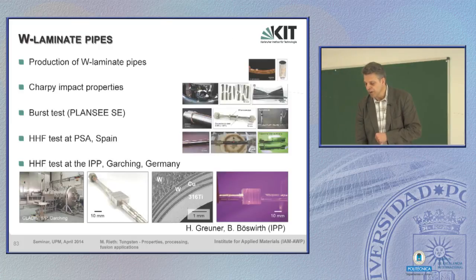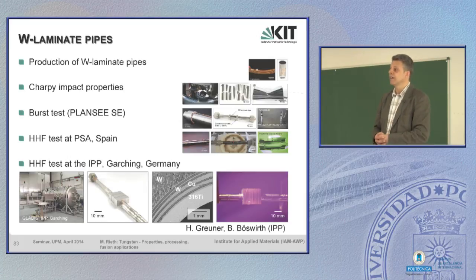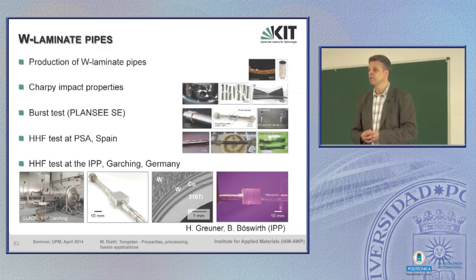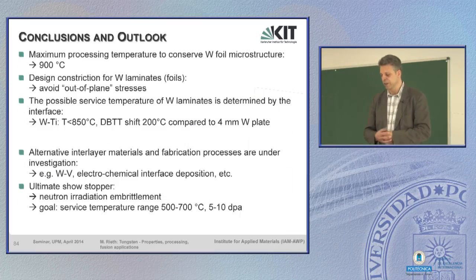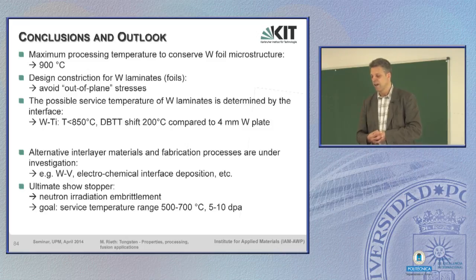shows a worst case scenario where we have used a stainless steel pipe, which has not the very best thermal conductivity and bends very strongly under such heat loads, but still the tungsten cover layer in between fixed the differences of thermal expansion, as we have seen. So in general, we have done all the technology. Of course, it's still a long way to go to fusion reactors, but the conclusions and outlook are that we can have a material at least up to 900 C.